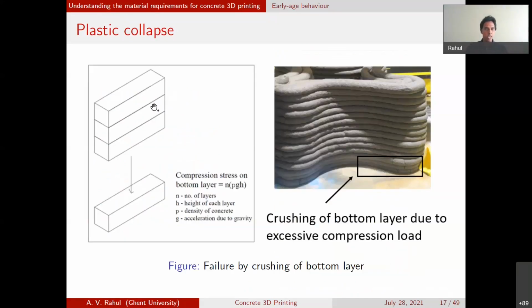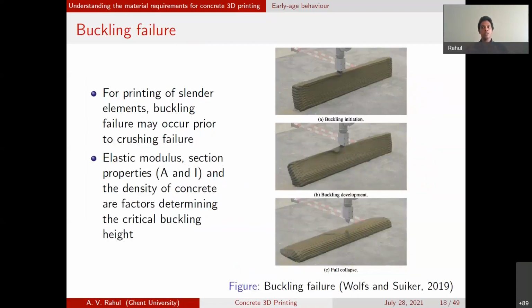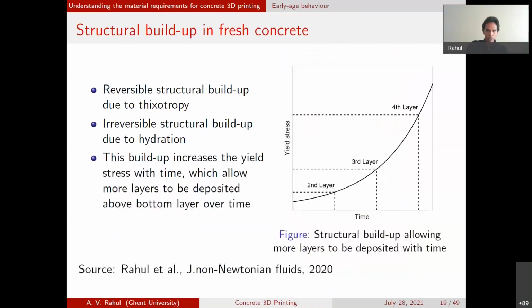One is the amount of stress that it can withstand, or let's say the compressive strength of the fresh material. The other is the modulus value of the fresh material. How much is the modulus value, so that if you have a given print geometry and you're printing at a particular speed, is this modulus sufficient to prevent the failure of the material? So both these parameters need to be characterized.